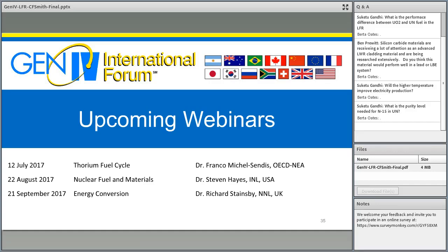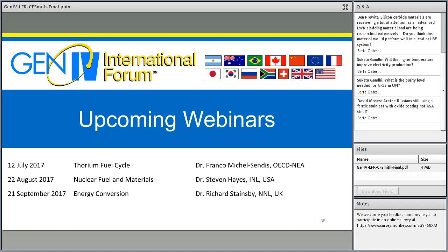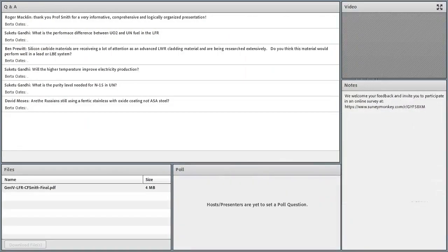So the question is, are the Russians still using ferritic steel, stainless with oxide coating, not ASA steel? So I don't have the up-to-the-minute answer to that question, but the Russian design relies heavily on control of oxygen content in the coolant to maintain the oxide coating on their components, and I believe it's a silicon-enhanced steel that they're using, but they rely very heavily on oxygen control.